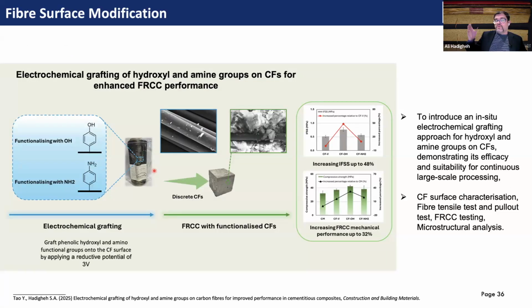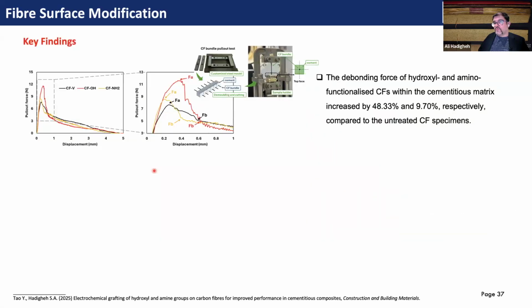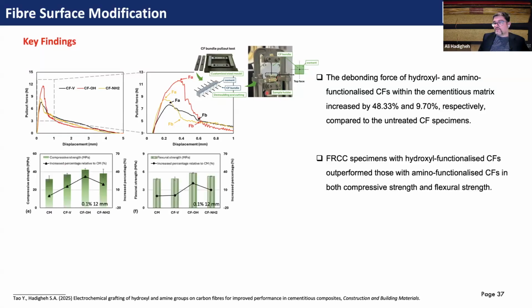But if we want more high-end composites and surface modification, for example, in situ surface modification during the production of carbon fiber, obviously electrochemical grafting is one of the good options. And we again worked on those hydroxyl and amine groups to functionalize the surface of carbon fiber and then see how that performs. We looked at the interfacial response when we pull the fiber from the concrete, and then identify the interface and pull-out force and so on. So it was quite successful, and we saw that mostly hydroxyl groups are doing better than amino-functionalized carbon fiber.